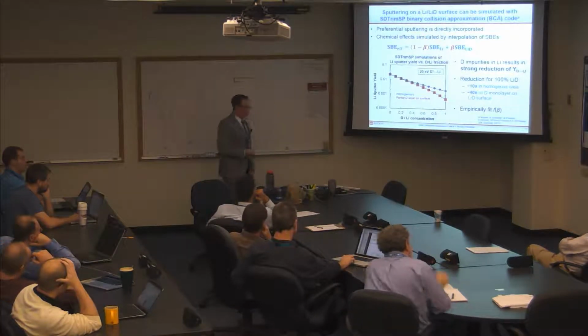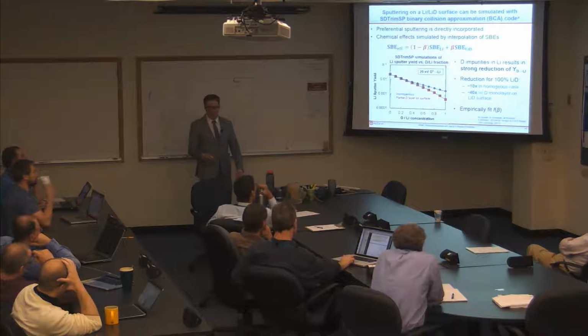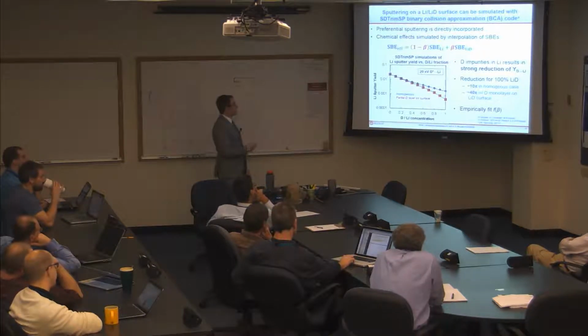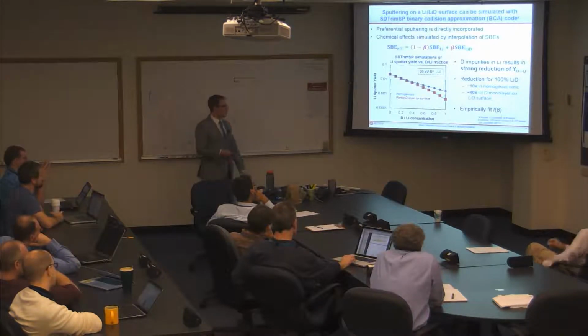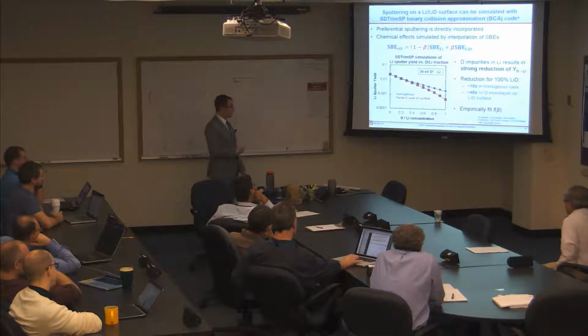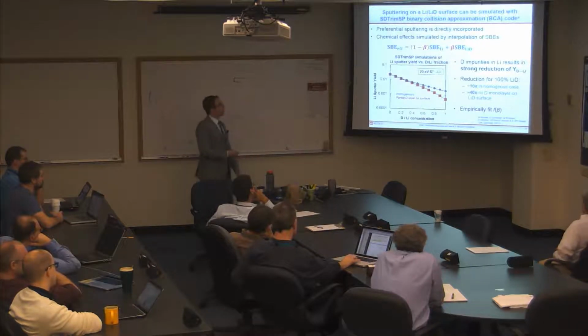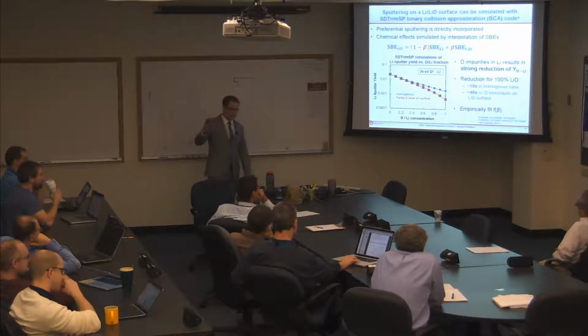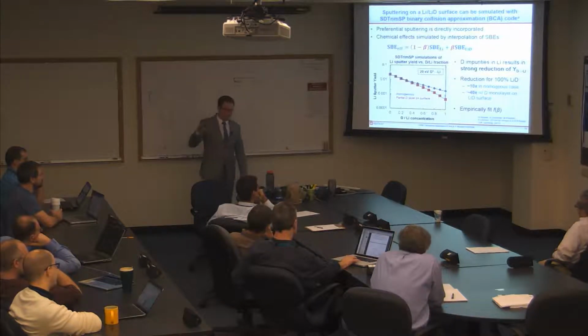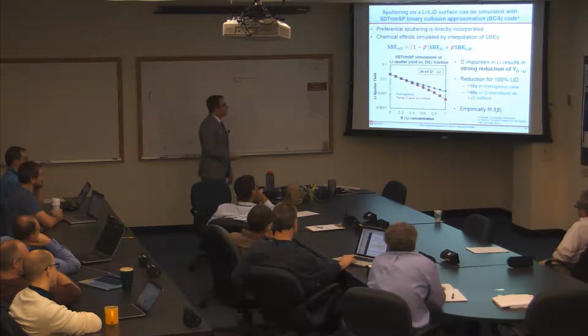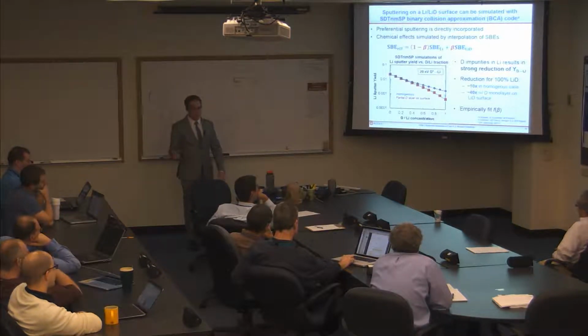So the way that we actually calculate the reduction of the sputtering yield that occurs because of preferential sputtering is by using this SDTrimSP binary collision approximation code. This is a very standard tool that people use in a lot of sputtering calculations. And you can incorporate preferential sputtering directly because you can specify the concentrations of deuterium and lithium on a monolayer by monolayer basis in the surface. So if you want to say I have a half deuterium monolayer on top of the surface or something like that, you can do that. And you can in some way incorporate chemical effects by changing the surface binding energy of the surface.